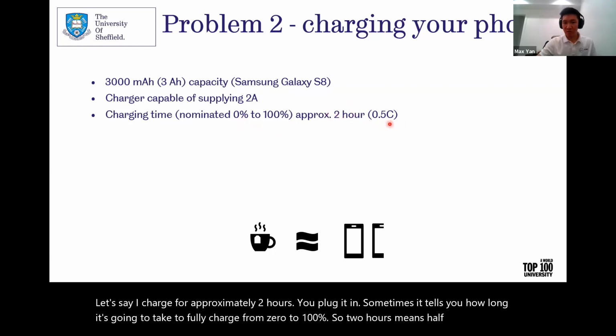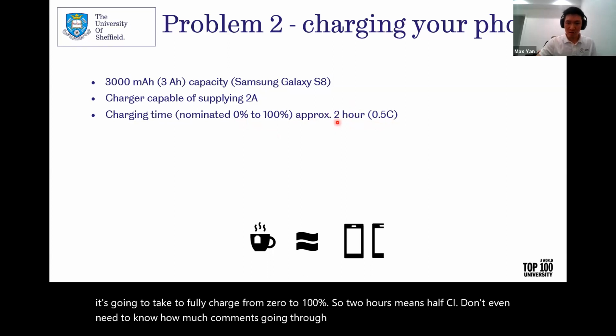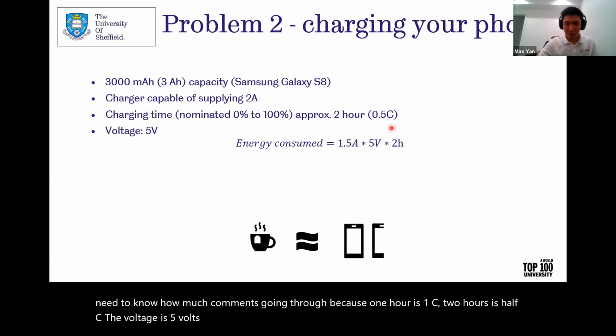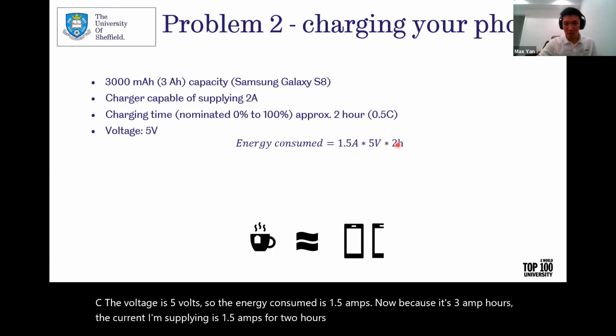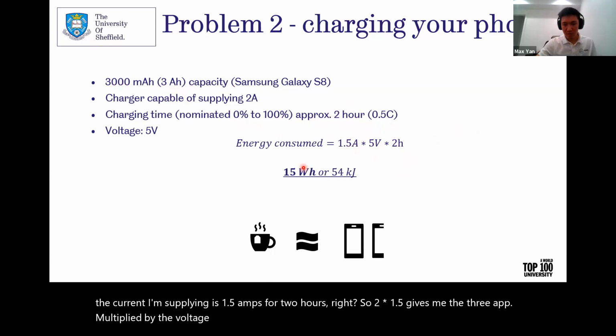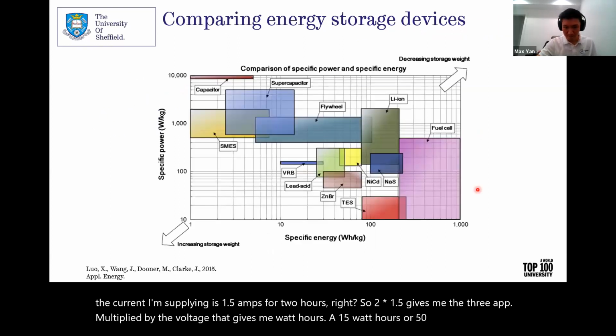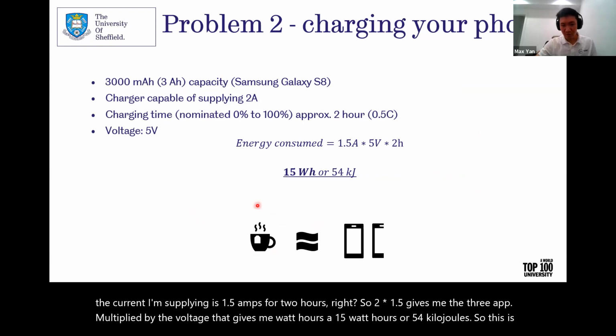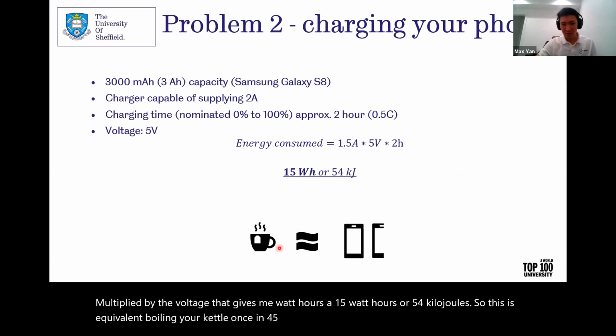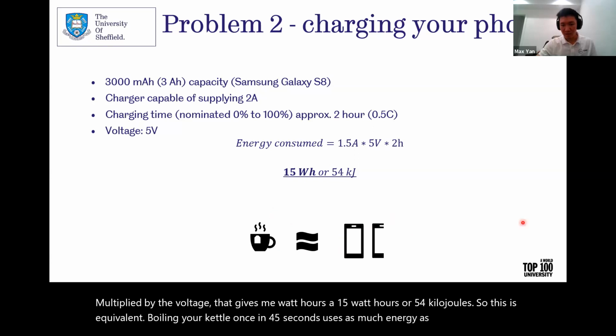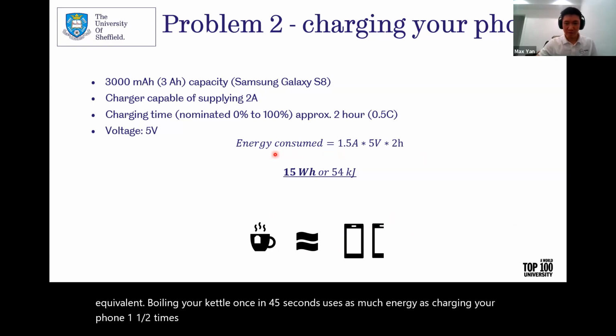I don't even need to know how much current's going through because 1 hour is 1 C, 2 hours is half C. The voltage is 5 volts. Because it's 3 amp hours, the current I'm supplying is 1.5 amps for 2 hours, right? So 2 times 1.5 gives me the 3 amp hours. Multiplied by the voltage, that gives me watt hours, 15 watt hours or 54 kilojoules. So boiling your kettle once in 45 seconds uses as much energy as charging your phone 1.5 times. So this is how you can very easily convert.